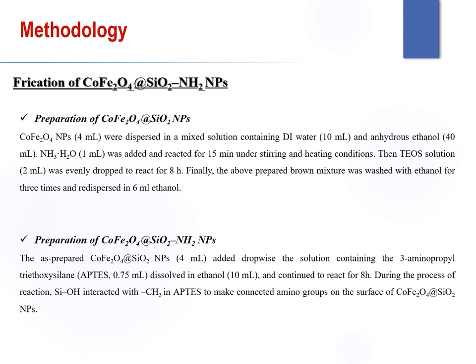Finally, the above-prepared mixture was washed with ethanol 3 times and redispersed in 6 ml ethanol. The cobalt silica nanoparticles were then added dropwise to a solution containing APTES dissolved in ethanol and continued to react for 8 hours.